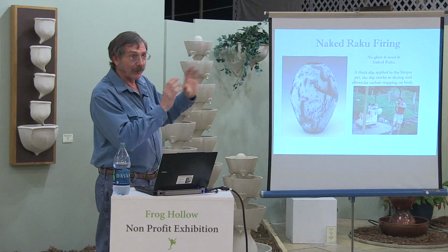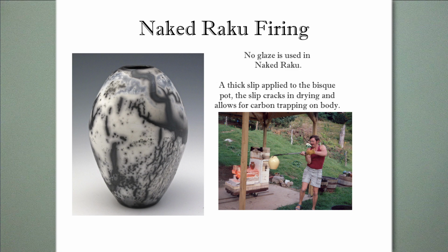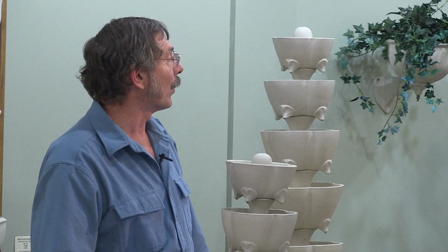I burnished the piece, bisque fired it, put a thick layer of clay slip on it, and fired it a second time. The slip cracks, carbon gets through it, and you get essentially a very similar look to a crackle glaze, but it's not even glazed. I mean, how much simpler can you get? There's no glaze. It's fired to a low temperature. They're, again, a visually pretty object, but really more of a work of art than what I tend to lean toward, which is vitrified stoneware, which gets me into where my life is today.